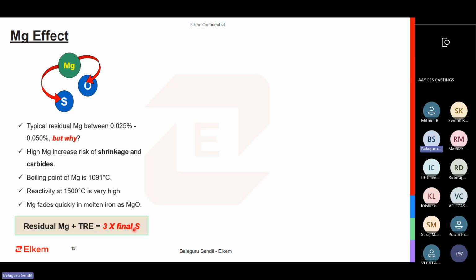It basically says that however much your final sulfur is, three times that is what I should have as my magnesium. So when people say, or when the common narrative is, I should have a minimum 0.030 residual Mg, it is being estimated that you have a sulfur of 0.010. So the relationship between magnesium and sulfur is very important.